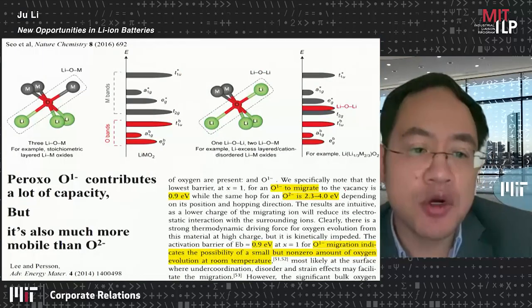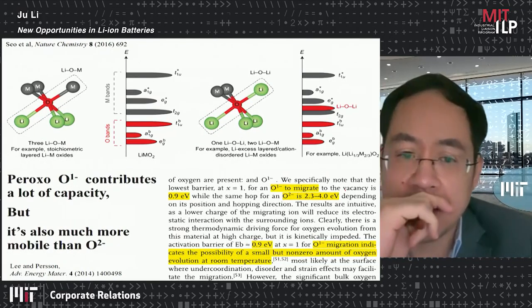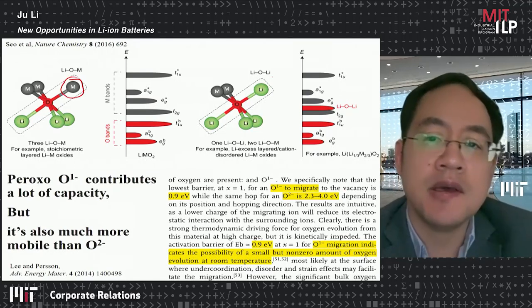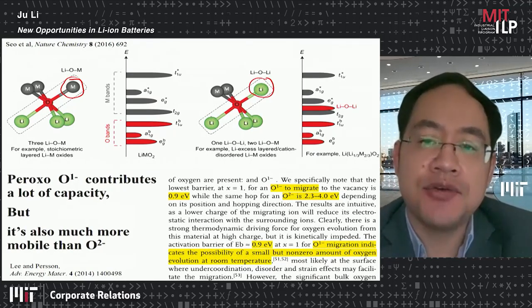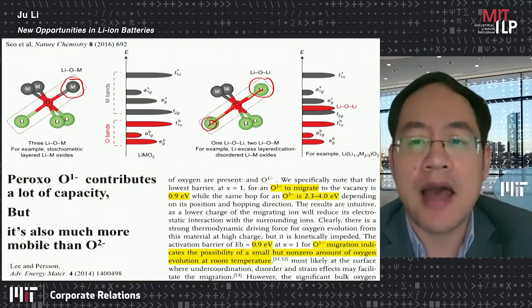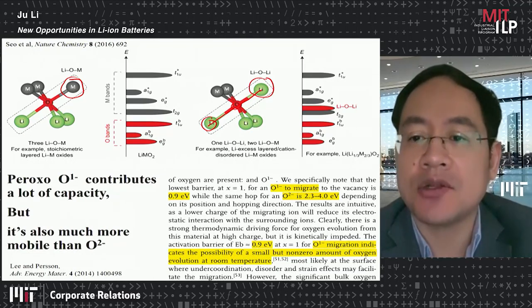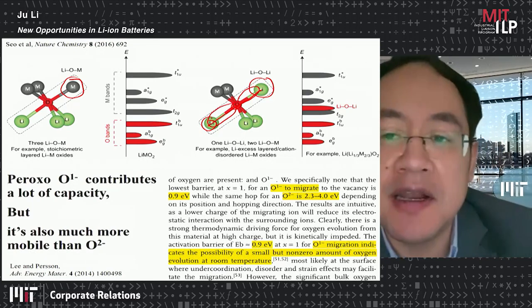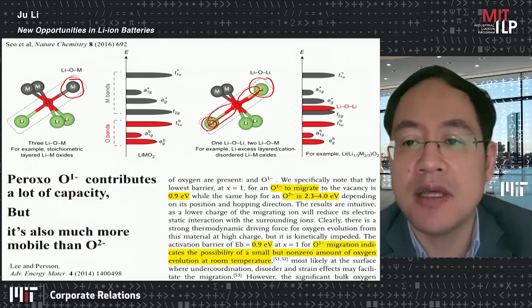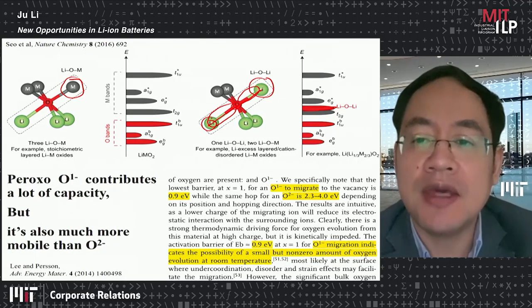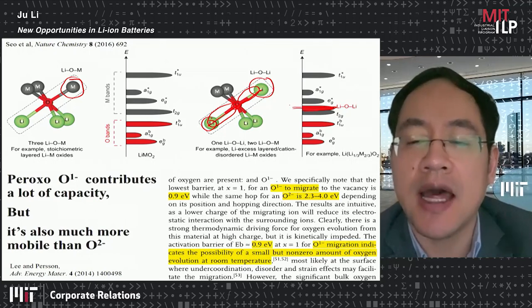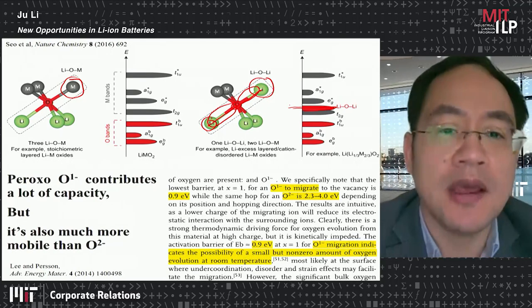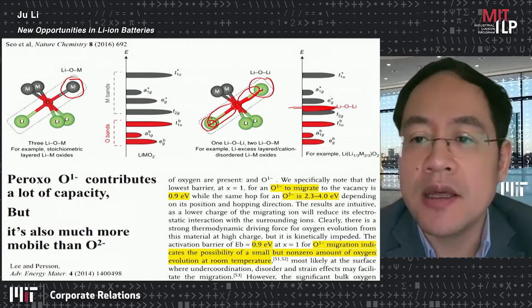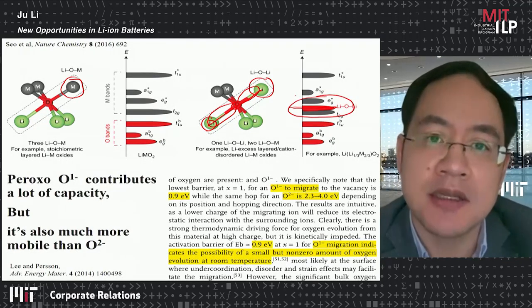And the general problem is the following. If you replace the transition metal by a lithium atom, then you create this lithium-oxygen-lithium axis, which has been shown to elevate the oxygen level. So you're going to have this oxygen p orbital that's less covalently bonded and more ionically bonded. And the result is you're going to shift the oxygen density of states upward. And that makes it easier to use the oxygen redox at a little bit above 4 volts. And you're going to be able to use the oxygen capacity together with the transition metal capacity.